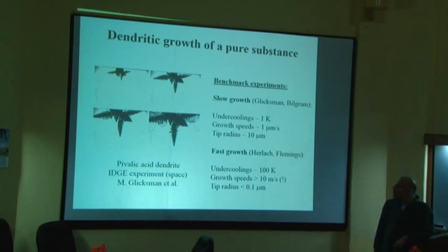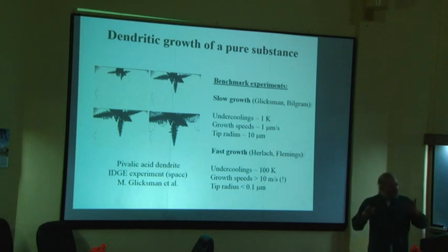And we are very close to the approximation that I have made, namely the density is approximately the same in the two phases. Since it's a pure substance, the only extensive quantity that is different between solid and liquid is the internal energy. So this growth process is limited by the flow of heat, because when the liquid crystallizes, the latent heat is set free, and this heat has to be evacuated.